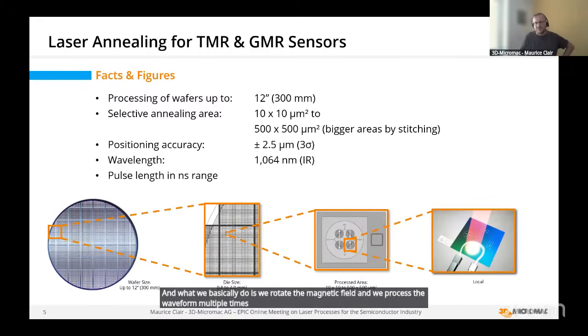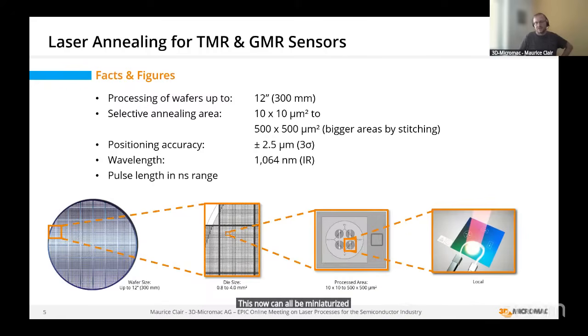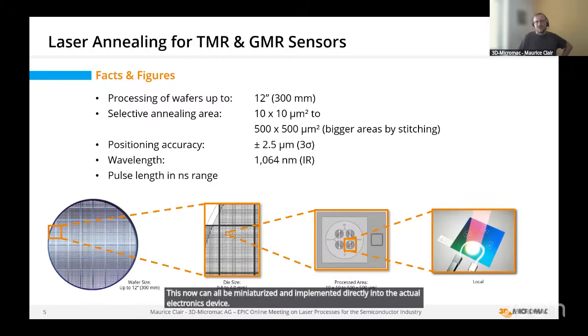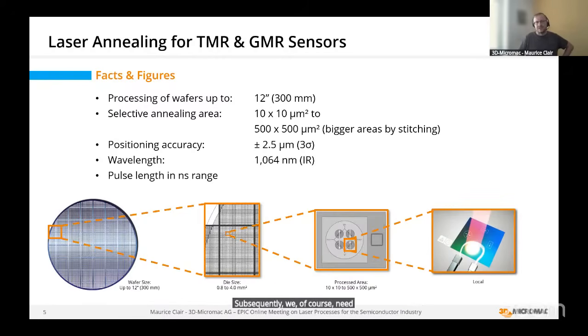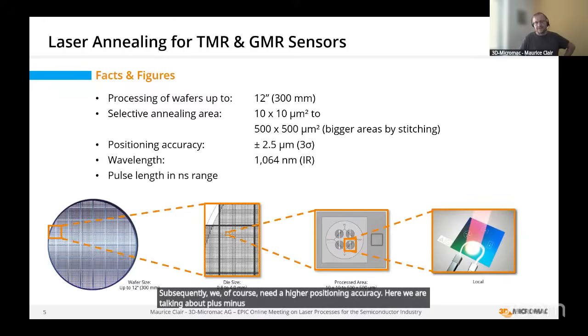And what you end up with is an in-device GMR TMR sensor, which previously had to be processed separately and then per pick and place had to be put together. This now can all be miniaturized and implemented directly into the actual electronics device. Subsequently, we of course need a higher positioning accuracy. Here we are talking about plus minus 2.5 micron with 3 sigma. So 1 sigma of give or take less than a micron.